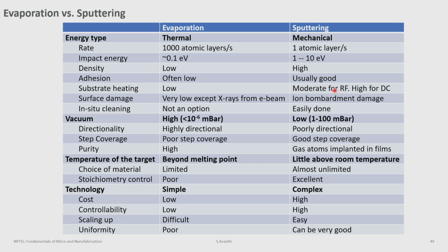The surface damage during evaporation is minimal because the energy of the incoming atoms is so low. In sputtering, it is significant. In situ cleaning is not an option without additional hardware. In sputtering, it is. The vacuum in evaporation tends to be higher. In sputtering, the vacuum tends to be low, which basically means the directionality is very, very high in evaporation, not so much in sputtering, which means that the step coverage is poor in evaporation, very good in sputtering. Purity is higher in evaporation because of the lower pressures. In sputtering, it is lower because of the higher pressures.